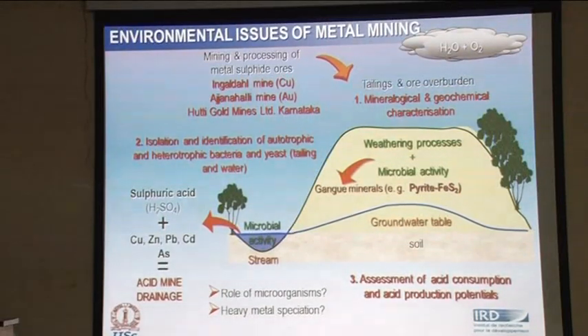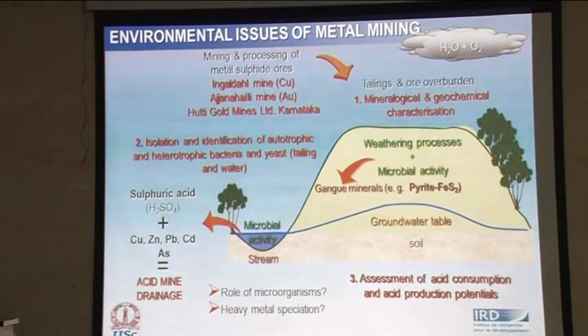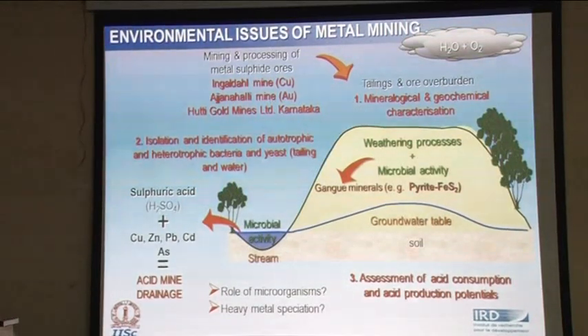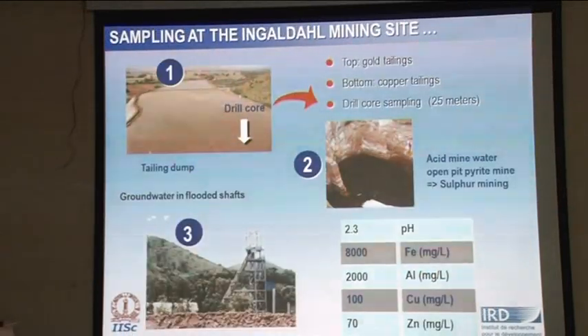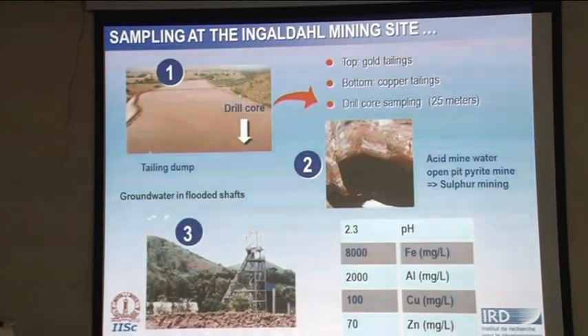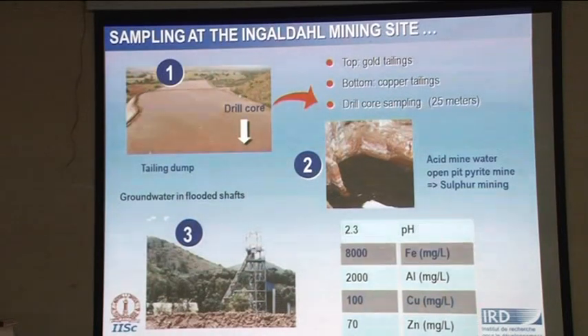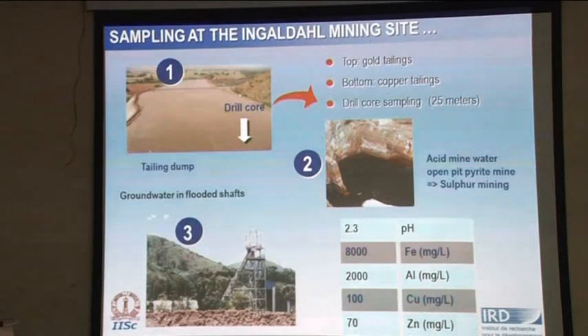So we wanted to look at the acid consumption potential of this tailing, and we did this test over a period of time in column studies. And then we have also isolated the microorganisms which are present in this natural dump, so we could identify not only the autotrophic organisms but also the heterotrophic bacteria as well as the yeast. So you will see here, this is the dump, the brownish one is what is presently dumped over the copper tailings. These are actually the processed gold tailings.